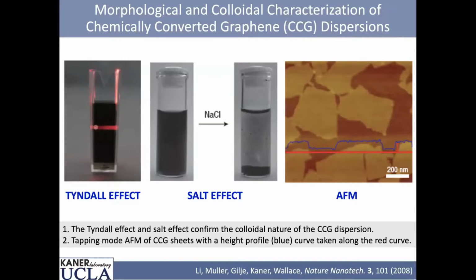But in fact, you see the red laser light. And the reason is because this is a dispersion. There's individual graphene sheets floating around in the water. Now, why do they stay as a dispersion? Well, they all have a negative charge on their surface, so they stay away from each other.